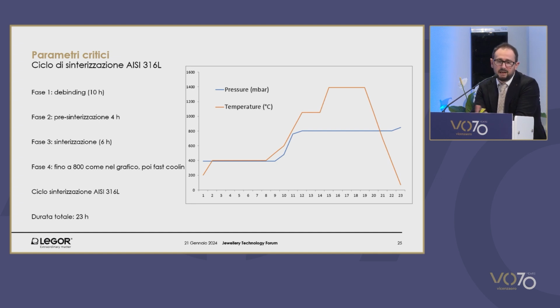And the phase of densification takes place in the upper part of the curve, so about 1400 degrees. If the item doesn't have any specific problems, the cooling curve can be the one that you can see here, and then fast cooling can continue. So the cycle usually has a duration of 23 hours for steel. It is a pretty long cycle.